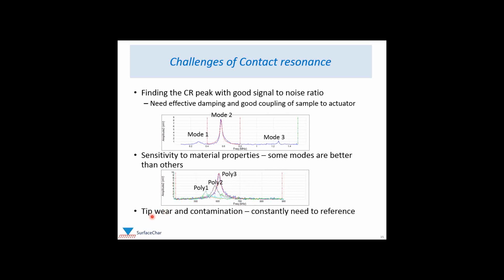The final practical challenge is tip wear and contamination. And it's a significant challenge in contact resonance, and it basically requires you to reference your measurement frequently.